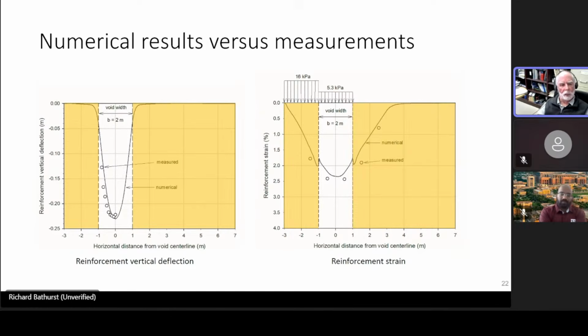So what you see on the left-hand side, the white bit here is the void, and the symbols are the measured vertical deflection of the reinforcement at end of construction, I believe. And then the solid lines are our numerical approximation to the measured deflections. And you might agree with me that that's not too bad, the agreement.